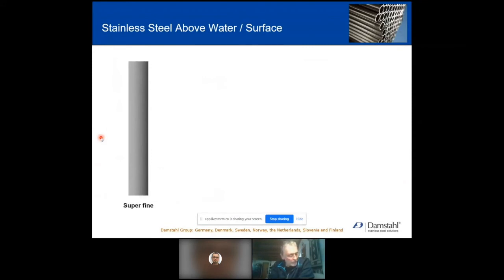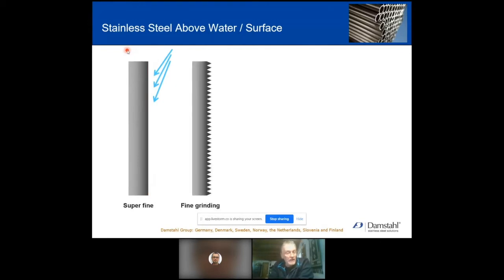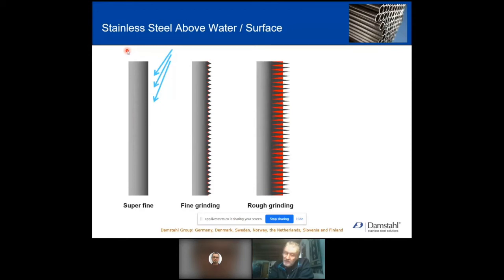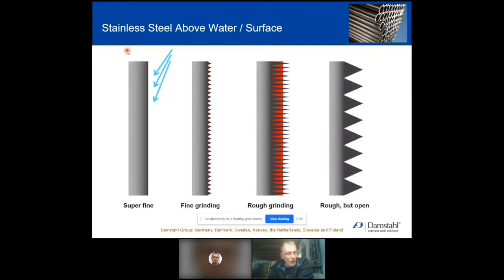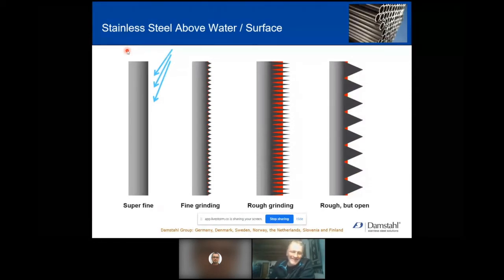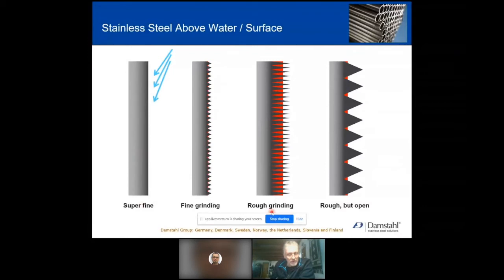Why is the surface so important when we talk about things above water? If we have a super fine surface and we soil it with some kind of product, it could be disinfectant, whatever it is, once we rinse it, we get an almost perfect process, no problem here. If it's finely ground or polished, then we'll soil the surface again, try to clean it. We don't get all of it off. There's still the residue, and of course, it's in the bottom of the ditches. Rough surface, a lot of residues. It's rough, a bit more open, then we are usually a little more successful. But you can see that the contact time is actually very, very dependent on the surface.